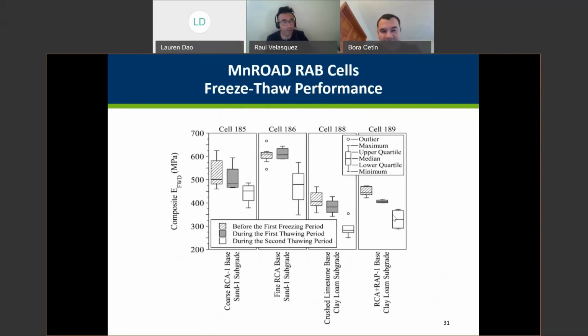Of course, having a sand subgrade will have a slight impact, but we also did the layered analysis. So we did predict the elastic modulus of each layer separately, and that ends up giving the same trend. Again, yes, composite elastic modulus may change, but layer-based elastic modulus were the same. Coarse RCA and fine RCA perform better than the RCA-RAP mixtures, and RCA-RAP mixtures perform better than the limestone.